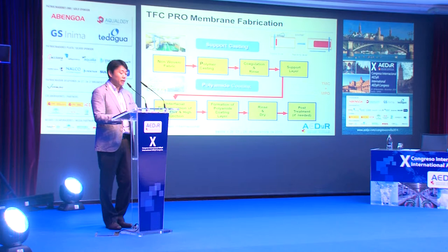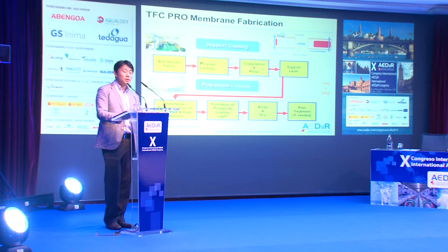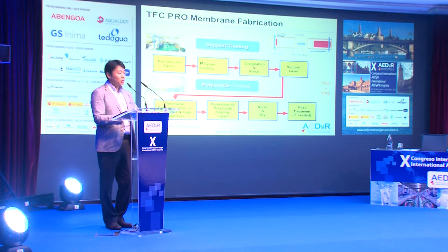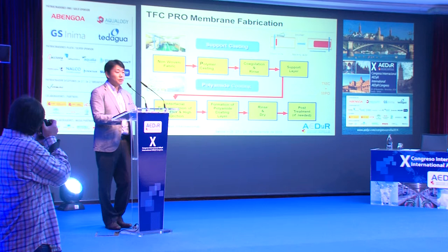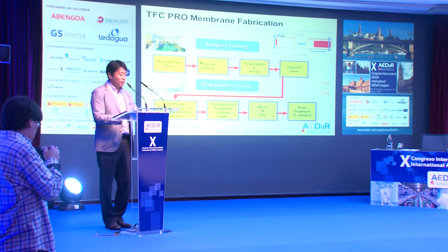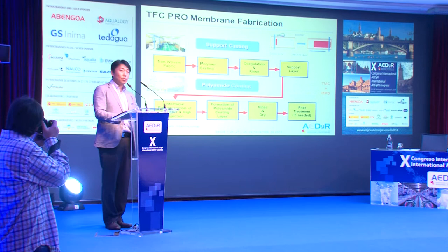In the case of a separation membrane using osmotic pressure, such as PRO or FO membrane, the fabrication of the support layer is very important. As the support layer is made by using hydrophilic polymer material, it can reduce the ICP. The hydrophilicity of the support layer can improve the effective osmotic pressure across the membrane. Also, the active layer has a thickness of 200 nanometers. It can be controlled for a higher A value and low B value.